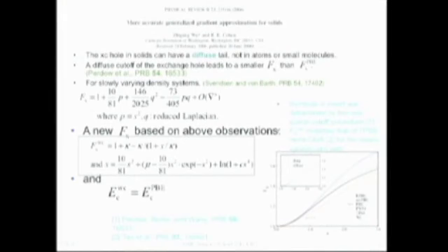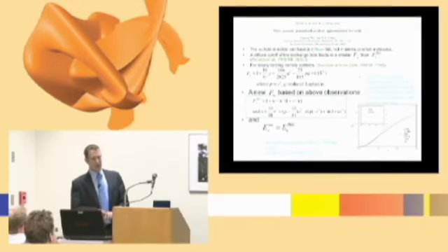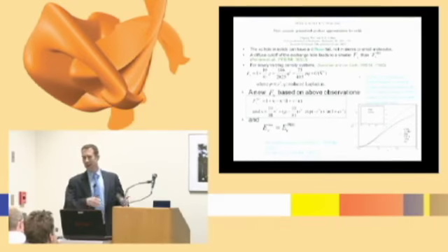I'll show the rationale for this in a minute, but the reason was that we were working on ferroelectrics, and if we looked at a material like lead titanate, which is a classic ferroelectric, if we applied the LDA, we got quite a good result compared with experiment. If we applied the traditional PBE GGA, it was disastrous.